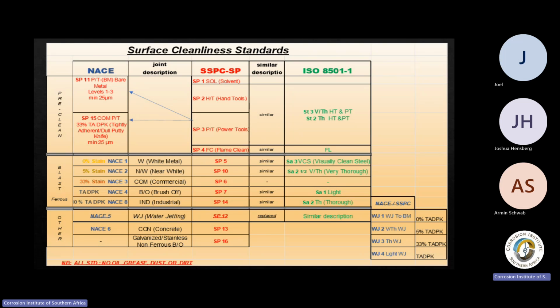When I use the surface tolerant coating, why do you like to clean that perfectly? If you've got rust underneath the surface, it actually forms a film. And if you put a coating on top of that rust film, the coating sticks to the rust film and it doesn't stick to the substrate. So you get certain degrees of what they call flash rust.